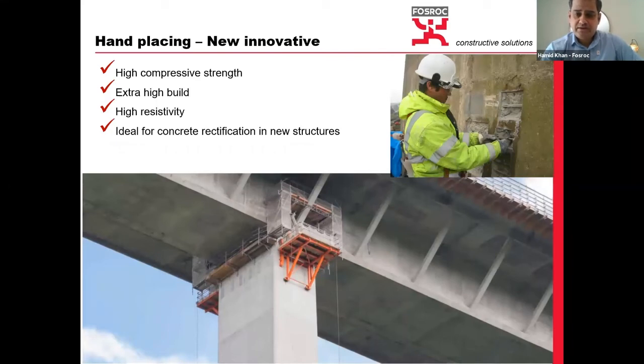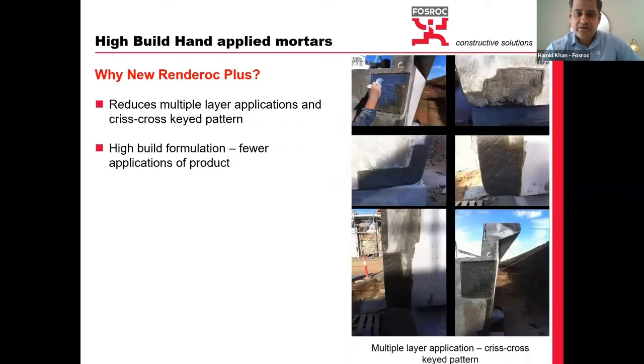Hand placing materials are there. This is a typical bridge girder picture, where you have a first layer of mortar, then you do the crisscross, apply a curing agent, and then apply a second layer. Now there are extra high build repair mortars available in the market, where you don't have to do so many build-up sections, and they can be built mostly in one section up to 80 or 100 millimeter in one go with excellent bond strength.